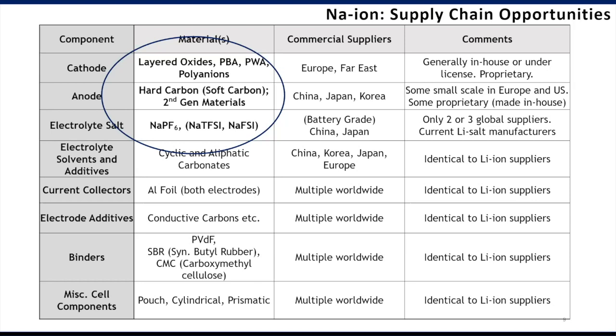In terms of anode active, I said to you that most people are using hard carbon, and there are maybe two to three commercial suppliers of large amounts of hard carbon. And hard carbon was originally manufactured for the lithium ion industry. There are small scale operations for manufacturing of hard carbon in Europe and in the US, but because the performance requirements and the morphology requirements are slightly different for sodium applications over lithium applications, some of the companies, including Faradion, are making proprietary versions of this hard carbon in-house, and that gives a benefit in the overall performance.